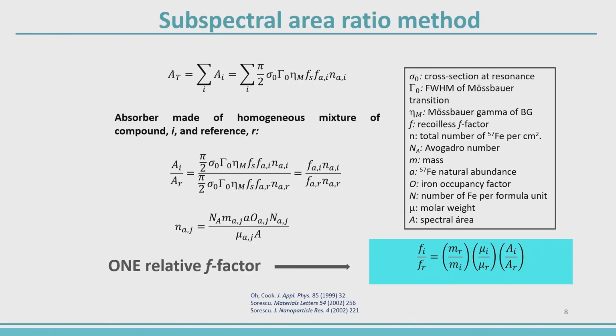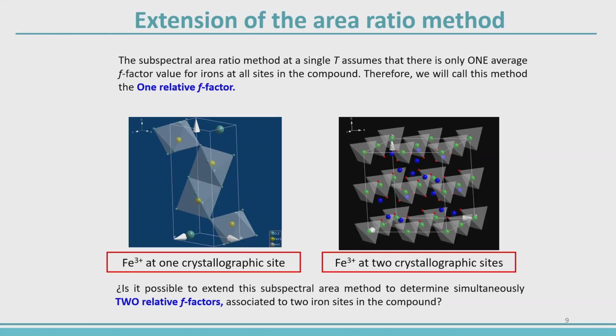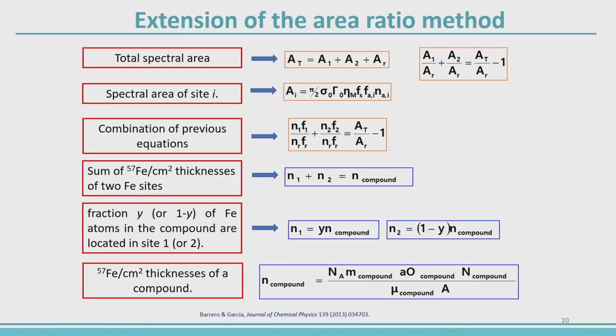But this is known. What we have proposed is that we have extended this formula to compounds that exhibit at least two different iron sites. This is the case of the ferrites, because iron is located in two different sites, the octahedral and the tetrahedral. The previous formula applies only to samples that show one specific iron site. It's an extension. So how did we start? We started with the spectral area. The total spectral area is the sum of the area of the first site, the second site, and the reference material. Then we divide both sides of the equation by the total area, which gives this.